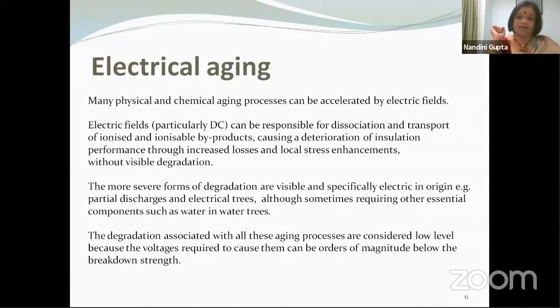That is one aspect. The second aspect is that there can be more severe forms of degradation, and those will definitely be visible. And those are the things that we talk about most of the time. For example, when we see partial discharges happening, we see electrical trees, we see water trees. These are degradation processes which are visible, and they require more severe damage mechanisms. But definitely, we need to study these mechanisms, and we do study aging due to partial discharge, due to treeing, due to water treeing. All this we do study. But we must remember that apart from these visible signs of degradation, there is a continuous degradation which is happening in the material due to physical and chemical aging under normal conditions.